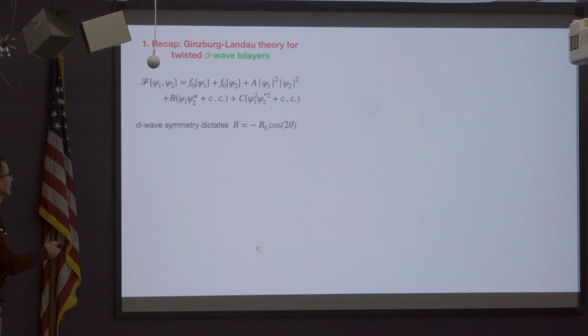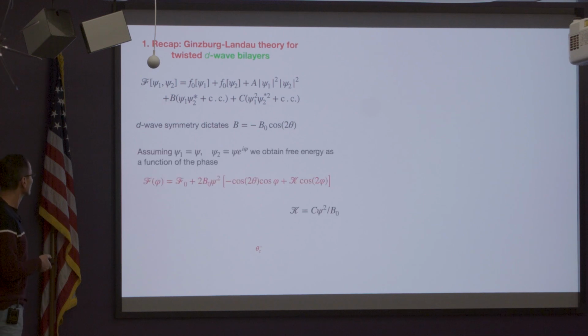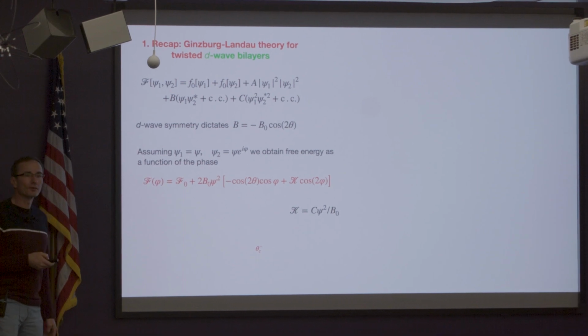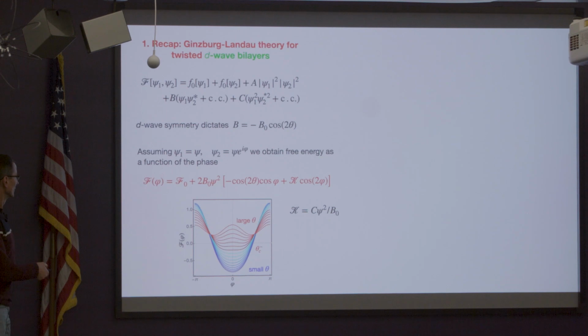90-degree rotation, and it vanishes when this angle is 45 degrees plus the usual multiples. Now, when we analyze this in more detail, we find this Josephson free energy that is only dependent on the relative phase between the two order parameters, and it leads to this landscape with 1 minimum at small twist angles and 2 minima at large